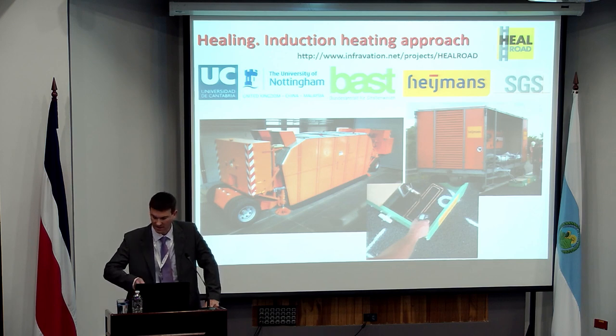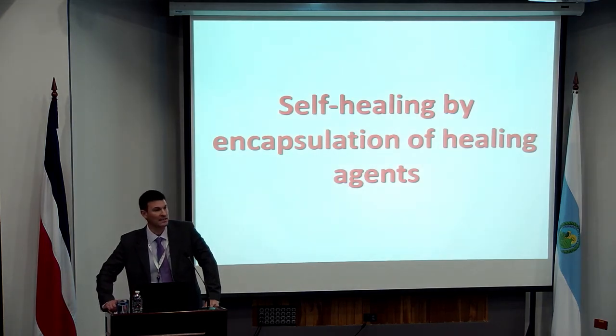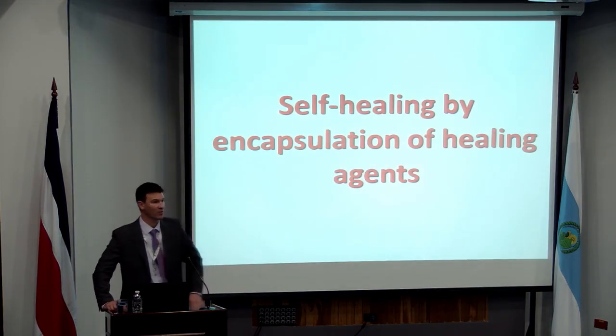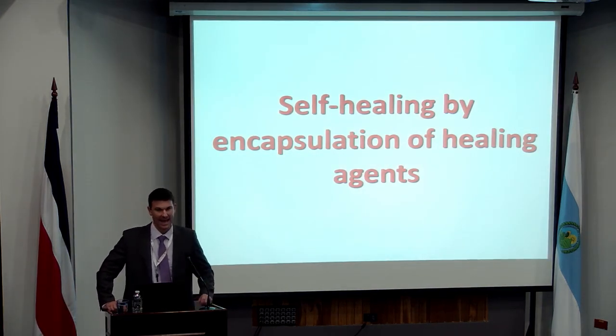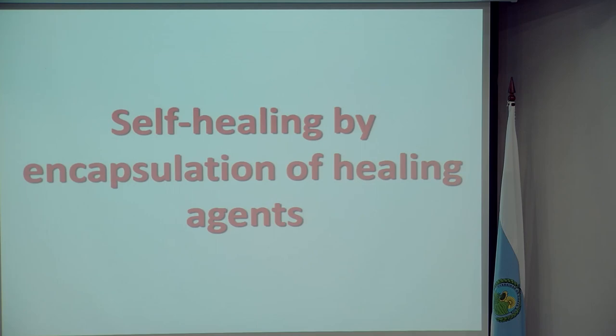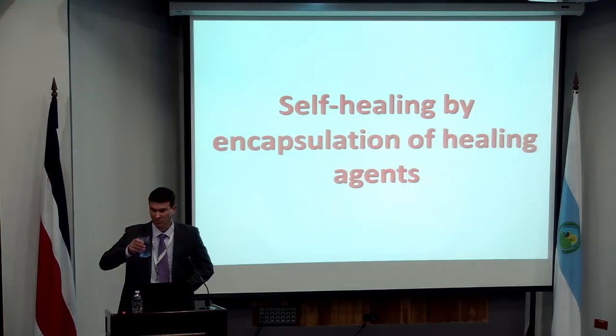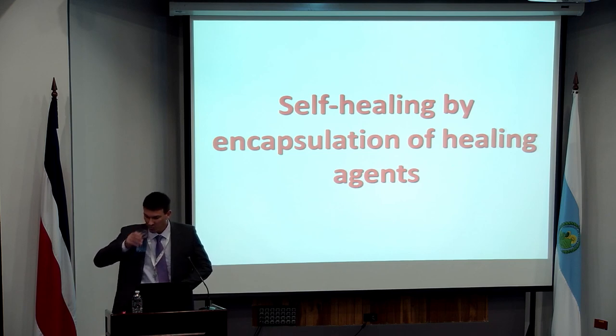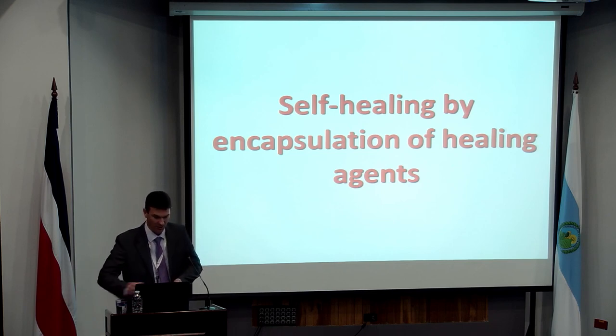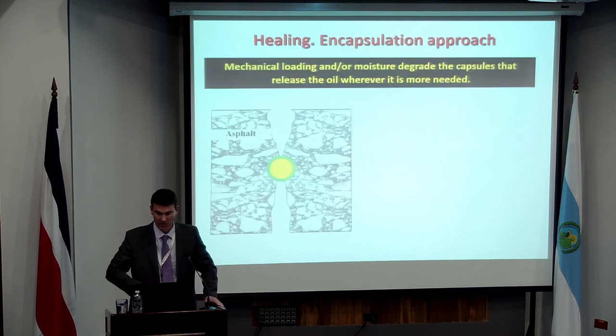So very quickly then, the last technology I want to look at is using encapsulation. In other words, saying, well, what happens if we add, at the beginning of when we're producing our specimens, some form of capsule that when it is damaged in terms of the asphalt, that capsule will release some form of healing agent. So again, it's not new technology. It's technology used in other fields in terms of construction materials. But obviously for bitumen or for asphalt, it has to have certain criteria.